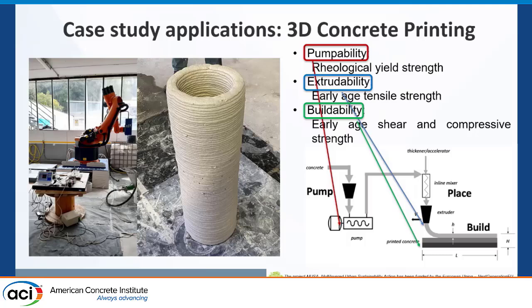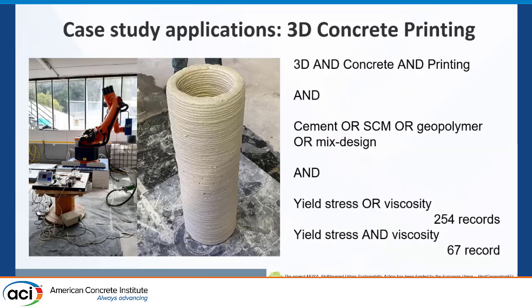Well, as a matter of fact, there are ways to correlate these requirements for 3D printability to fundamental properties of the material. The pumpability you can correlate to the Bingham yield strength. The extrudability you can correlate to the early age tensile strength because you are extruding a filament. So if the filament tears off, it means that you have exceeded its tensile strength. And buildability you correlate to early age compressive strength or Young modulus as well.